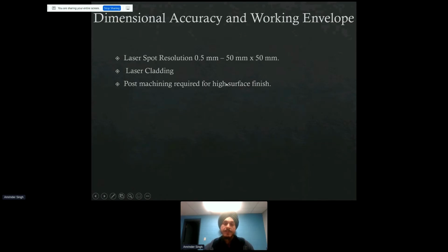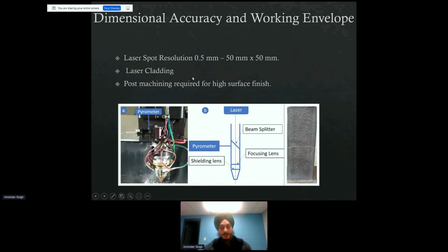Now let's talk about dimensional accuracy. Laser spot size in our facility can go from 0.5 millimeters to as big as 50 by 50. But at the bigger 50 by 50 spot size, we don't do cladding. For cladding, we have 0.5 to 6. We can do hardening in 50 by 50. And this is how this single layer, single wall is created by the system.